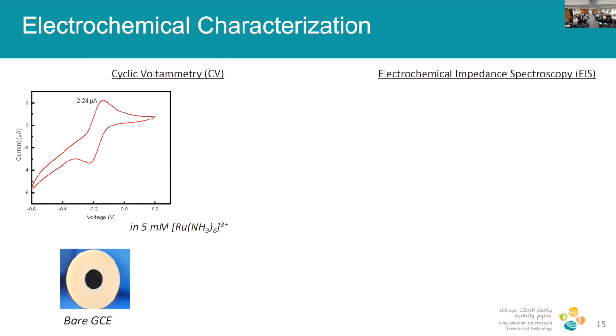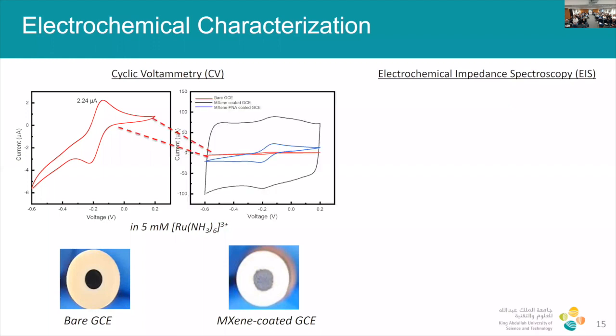Great. Now, if we deposit, actually just drop cast, our MXene onto the GCE, you do exactly the same experiment, you'll see in black this massive increase in current. So from 2 up to 100 microamps of current, which exactly tells us what we're expecting.